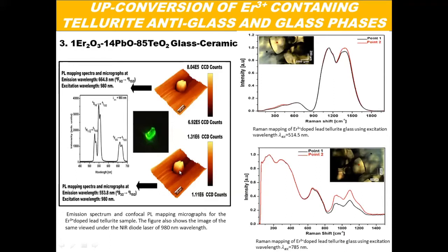And the inclusions and the matrix, their photoluminescence intensities are also the same. On the right hand side, you see the micro Raman spectra of erbium doped lead tellurite samples. We record the Raman pattern at the matrix phase, and also at the inclusion phase, which is shown by these dots in the photograph in the inset. This red dot is the point, and we record the Raman pattern at both the locations.